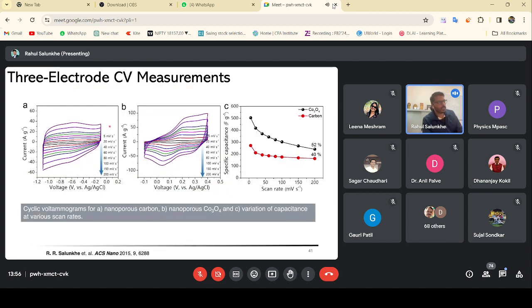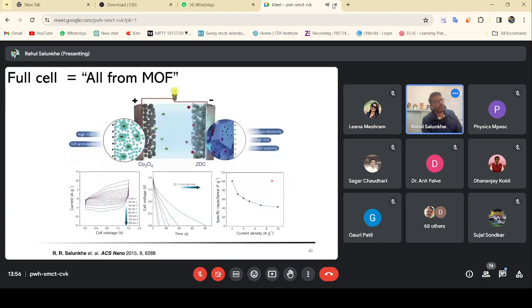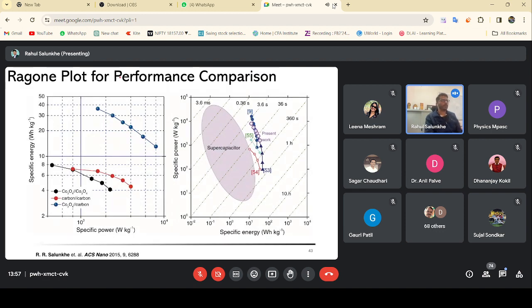Because of this, we carried out the electrochemical analysis and observed 82% retention for the cobalt oxide and 40% retention for the carbon material. Now we have cobalt oxide on one side and ZIF derived carbon on the other, which has very good conductivity, high surface area, and good stability. That's why we used this asymmetric combination and achieved a very good specific capacity of around 100 farad per gram. So this is the Ragone plot performance comparison. We can achieve a specific energy of around 36 watt hour per kg, which is much higher than that of other nickel or other polymer-based materials.